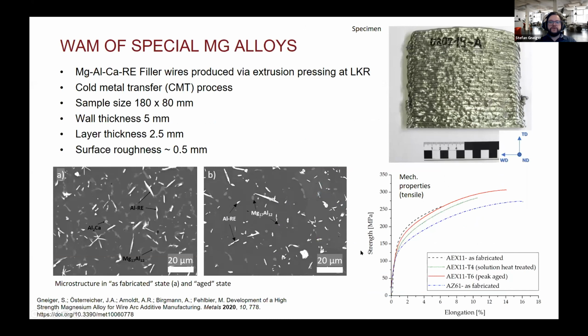After the commercial wire, we started working with our in-house produced wires, in this case, a magnesium aluminum alloy with additions of calcium and rare earth. Again, the cold metal transfer process was used to produce walls like this, with a wall thickness of 5 millimeters and a layer thickness of 2.5 millimeters. The deposition rate was higher here, so we also have a higher surface roughness.